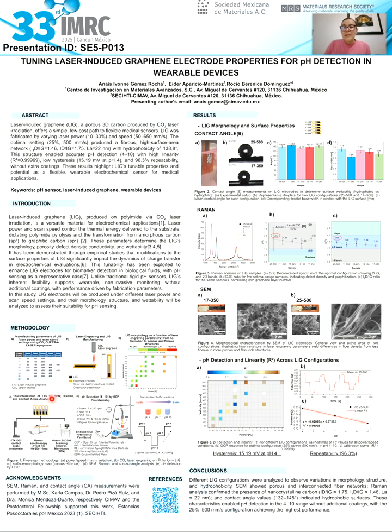First, we select different combinations of laser power and scan speed to explore a wide range of conditions, shown in table 1. Next, we engrave the polyimide surface using the carbon dioxide laser, forming the LIG directly on the substrate. Then, silver ink was deposited to generate the electric contact, and the passivation process was carried out. After that, the surface morphology was mapped, ranging from marked porous to marked fibrous structures, to determine which adhere to the polyimide substrate. In this case, the blue configurations show poor adhesion, whereas the green ones adhere successfully.